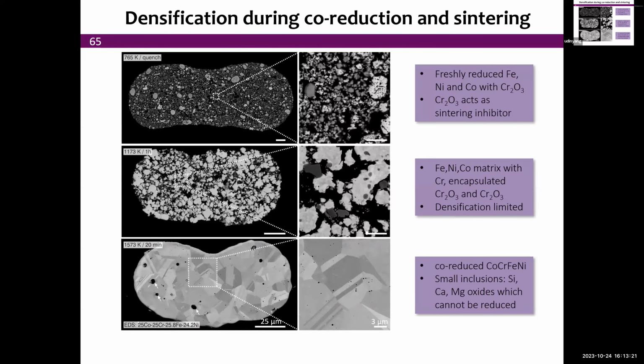And we can see this really in those interrupted structures. So here is the low temperature where you have freshly reduced iron, nickel, and cobalt, and you see chromium oxide particles that in fact inhibit the sintering. So they are simply preventing the iron, nickel, cobalt from sintering together, which is good. We need porosity to get access for the hydrogen to come in and reduce and the steam to come out.